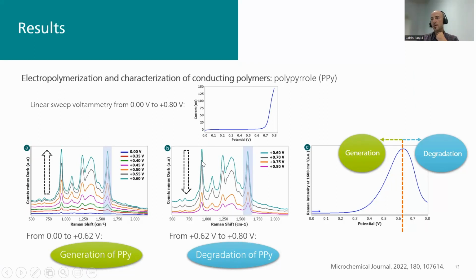In fact, what happens to these bands corresponding to the polypyrrole is that their intensity is going down at higher potentials. So we can see that the maximum signal is obtained at +0.6 volts, but at +0.8 volts, the intensity of the signal is going down. It is going down because we are over-oxidizing the polypyrrole and we are losing some of the structure.